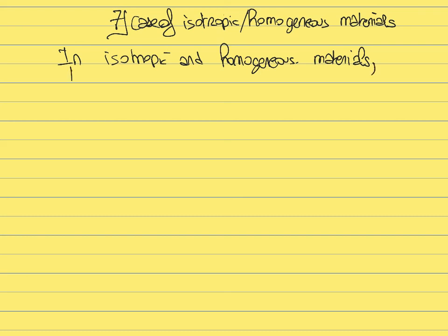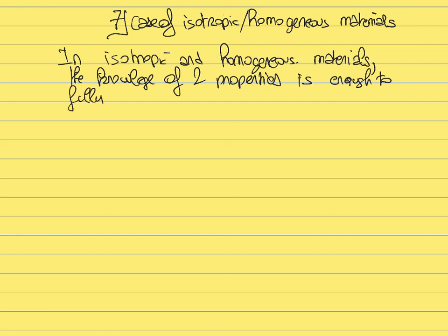Then in this case, the knowledge of two of those three properties, for example, both the Young's modulus and the shear modulus, or the shear modulus and the Poisson's ratio, is enough to fully characterize the elastic behavior of the material.